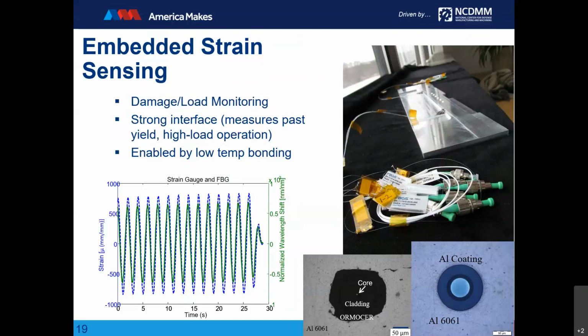So what we did is we printed the entire component, but we printed it with 6 fiber optic strain gauges. On each fiber, we actually had 6 locations where we could measure. So we basically embedded 36 sensors into this part, and we put it in a fatigue rig and studied not only the steady state cyclic loading as you see here, but we actually ran it out to failure. And in the fiber optic strain gauges, you could actually watch the plastic zone of the cracks as they approached the fiber optic until the fiber optic eventually failed. So it was a really interesting way to study and correlate a digital twin of a part where you have actual data from inside the part.